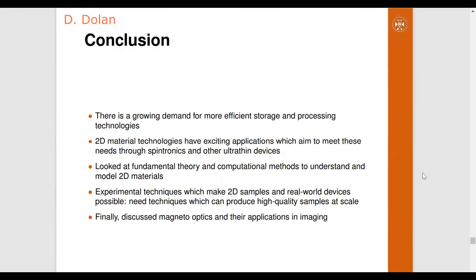We then moved on to some experimental methods used to produce 2D material samples, primarily exfoliation and thin film growth. Among these, liquid exfoliation and chemical vapor deposition stand out as being potentially scalable to high volume production. Finally, we looked at some of the magneto-optical effects displayed by 2D materials and their applications in imaging.